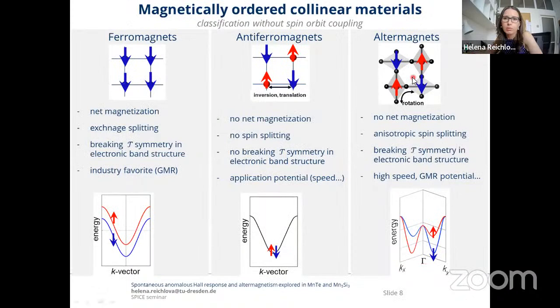Therefore, coming back to our table, we can add here one more class of materials, let's call them altermagnets, which have also the spins oriented up and down. The total net magnetization is indeed zero, they are compensated. However, the local crystal electric field is not connected, or is connected by rotation, and it leads to anisotropic spin splitting as demonstrated here, and breaking of the time reversal symmetry in the band structure.